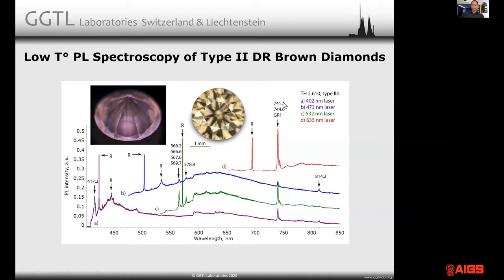You see many defects, a big overlap of the defects in type 2 and type 1 diamonds, except this broad band at 710 that I have not personally seen ever in a type 2A diamond. The reason for that is type 2A is not always type 2A. Type 2A contains some nitrogen, some more aggregated than others, so it can be very variable. It's basically a continuum from type 1 towards type 2, and since we can only determine the nitrogen content with infrared spectroscopy, it's kind of a limited sensitivity.